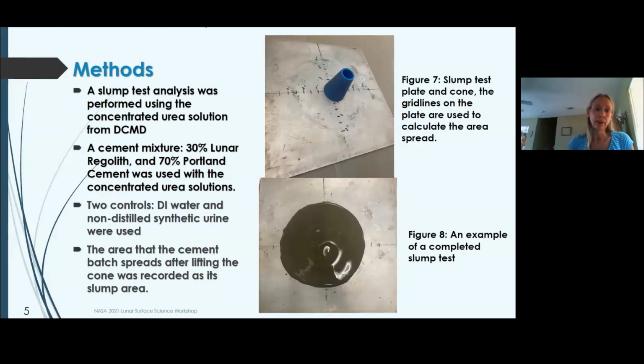What we did was a mixture of 30% lunar regolith and 70% ordinary Portland cement. And we tried different ways to see how workable or plasticized the cements were. To figure out how workable cement is, typically you have what's called a slump test. A slump test has a big metal cone. You put the cement in there, and then you just lift the cone off, and you see how much the cement slumps down. The more it slumps down, the more workable the cement is.